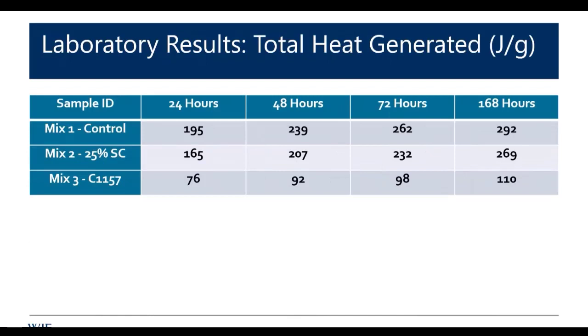Basically, total heat generated, again, is pretty important when you look at mix 3, right? With the addition of slag, we see a slight decrease as we would expect. Mix 3, it's not getting very hot. And that can help us in some applications. Doesn't necessarily help us on a tilt-up that we've got to tilt in 3 days, right?